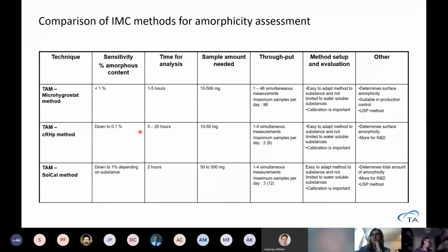We can see that the stepwise relative humidity change is by far the most sensitive, but with a good setup you can get very low sensitivity for amorphous contents also with the Microhygrostat method. Note that these two methods will tell you something about the surface that's accessible for the humidity on your particles, the amorphous part. But of course, that's often what happens when you process. It's the surface that you change.